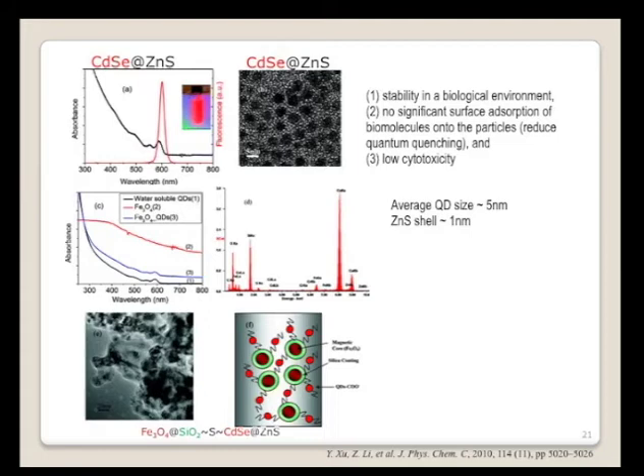Another thing is no significant surface adsorption of biomolecules will happen on the surface of this particle. This also has an advantage for the quantum efficiency of the quantum dots, because if the quantum dot surface is covered by biology molecules, the quantum efficiency will decrease. That's called quantum quench. So we still can get a high quantum efficiency. And the third thing I just mentioned, this kind of coating can lower the toxicity of the quantum dots.